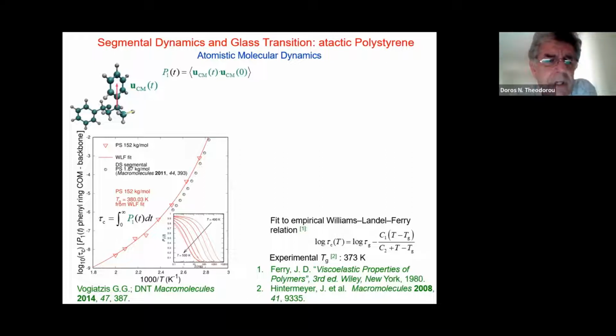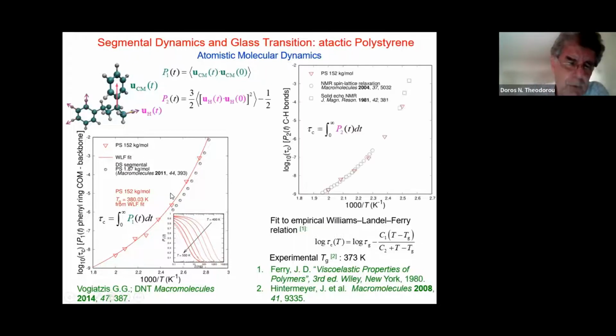Also shown here are measurements from a considerably lower molecular weight polystyrene. The simulated one was 152 kilograms per mole. The measured one, 1.87 kilograms per mole. And these gray points here are measurements from dielectric spectroscopy, which measures exactly this type of motion, and they parallel the measurements that were done in the simulation.